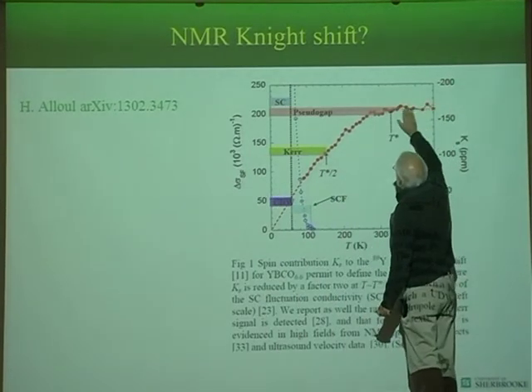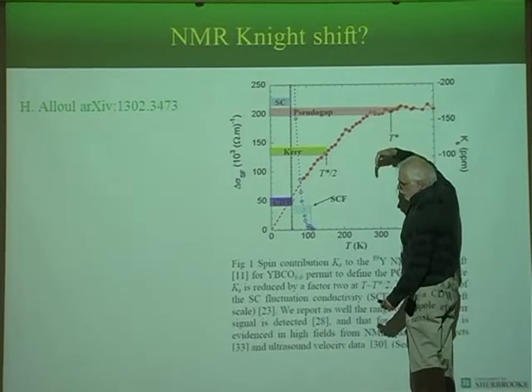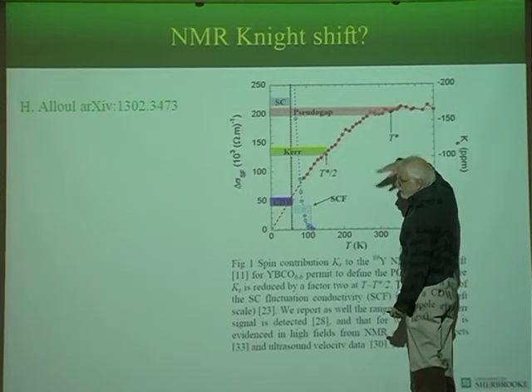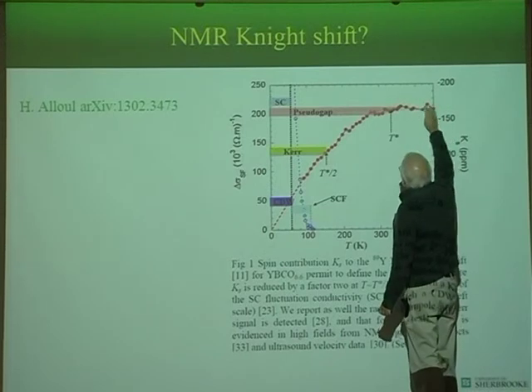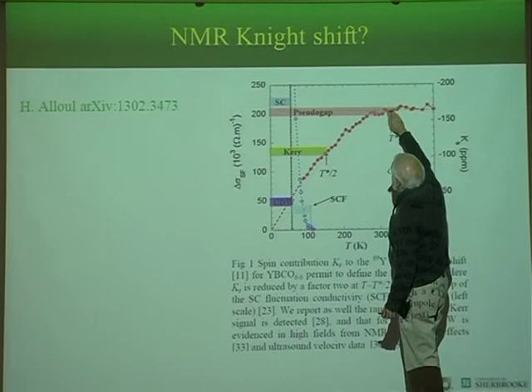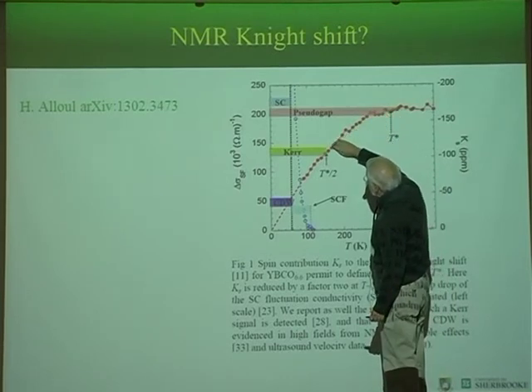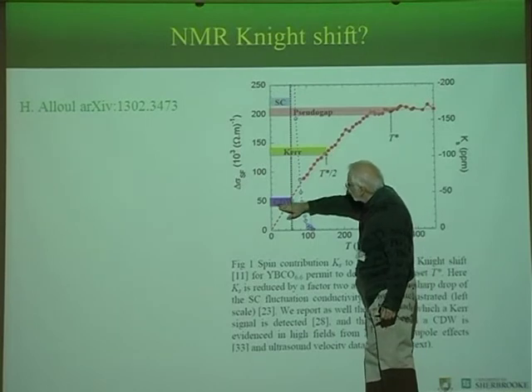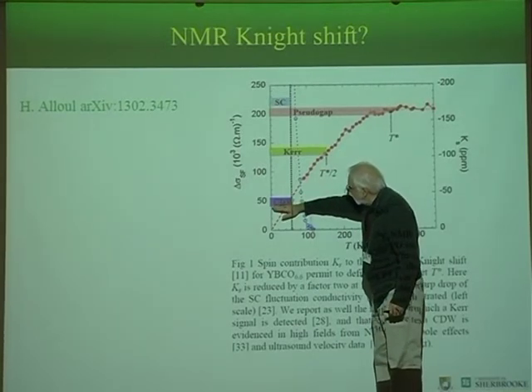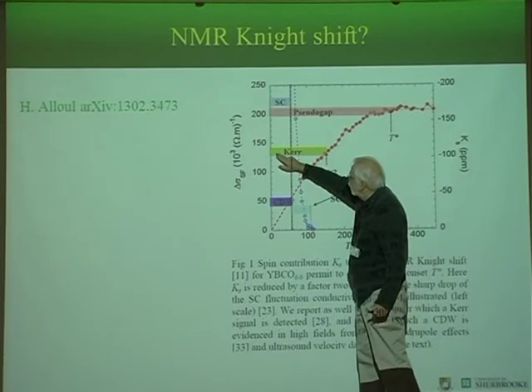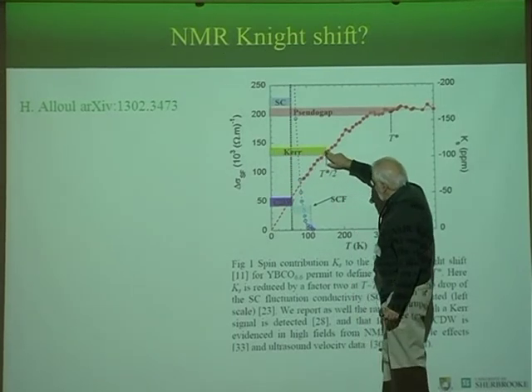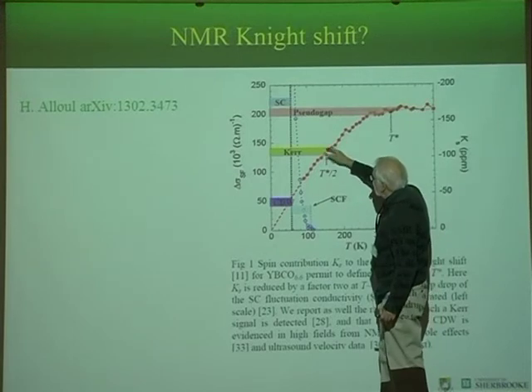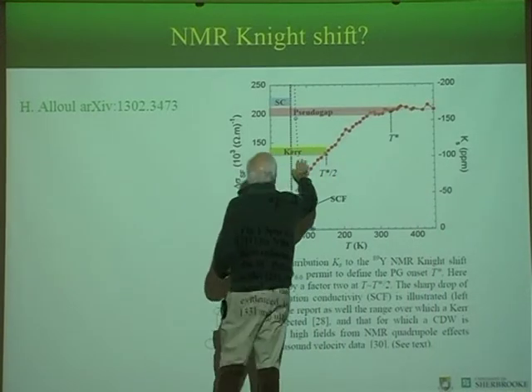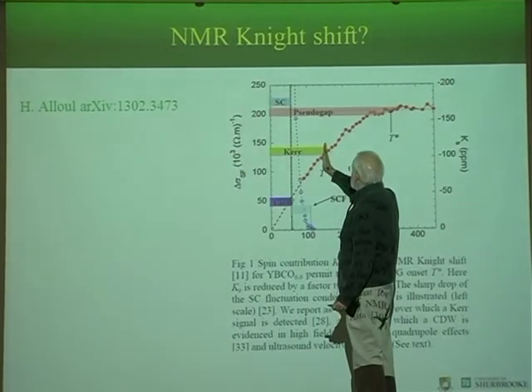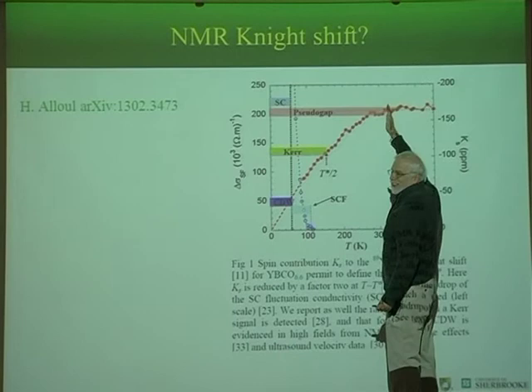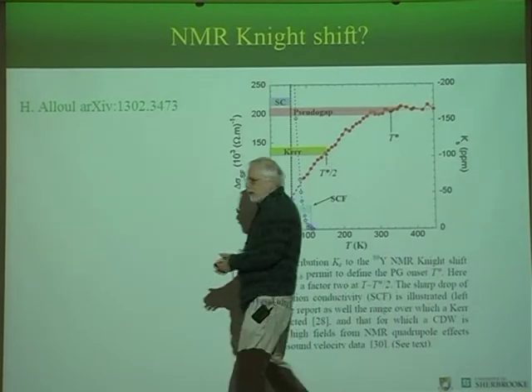you see the Knight shift here, this is the compound that's right above the doping where the charge density wave occurs at the highest temperature. So if we call this T star, you see that the Knight shift seems to have a strong temperature dependence before we hit the charge density wave transition. This was the measurements of Henri Julien. And now with these more recent experiments, this is shifted up here. And so there's a factor of 2 here. And there are other experiments I will talk about here in a moment. So there seems to be evidence of a real phase transition here, but this T star occurs way before this transition occurs.